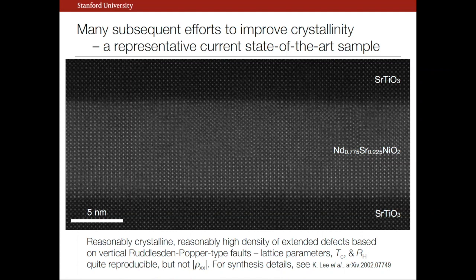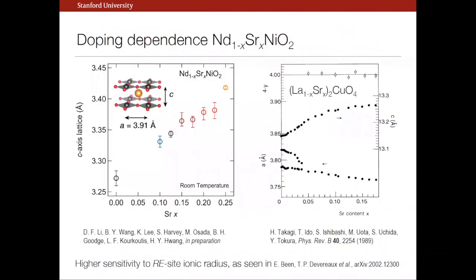And the upshot of that statement is that whereas bulk sensitive measurements like lattice parameters and nowadays Tc and the Hall coefficient are quite reproducible at a level I'll show you, the magnitude of the resistivity is still bouncing around a bit. Okay? And we speculate or attribute it to the details of the density and distribution of these extended defects. And so what I'm going to show you now is properties associated with the doping series, but this is kind of the landscape as far as we see, and not much changing systematically with doping.